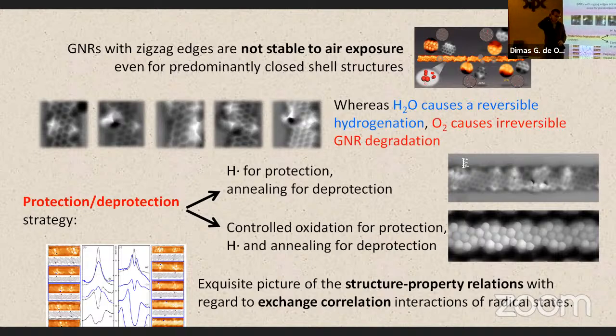Yes, and I have another one. Can you control the ribbons in such a way that you could put them parallel to each other on the gold surface? Yes, we have actually done that. If you want to do it macroscopically, instead of flat surfaces, you use periodically stepped surfaces. You use a miscut angle with respect to the flat 111 surface, and what you end up with is periodically spaced steps. And then the ribbons just like to align with those steps. That's something that we have been doing with these very ribbons, though I didn't show it here.